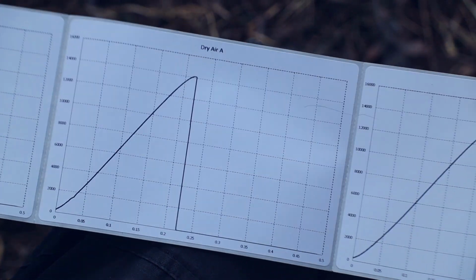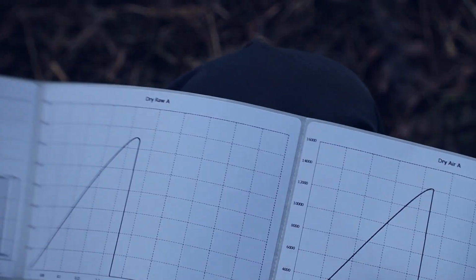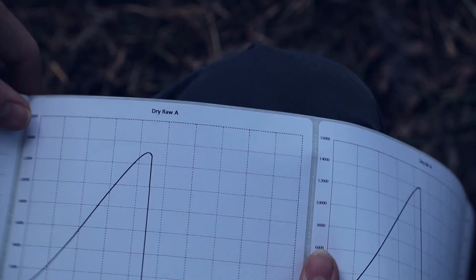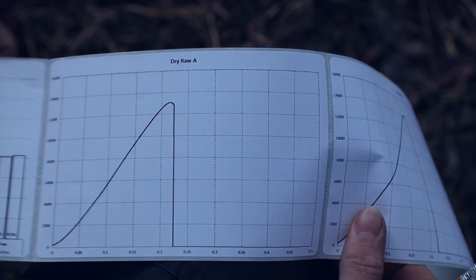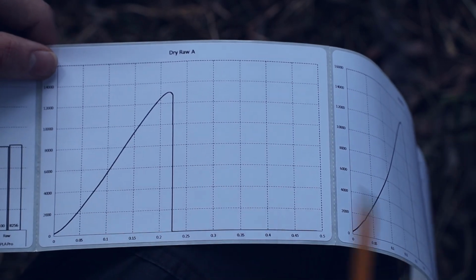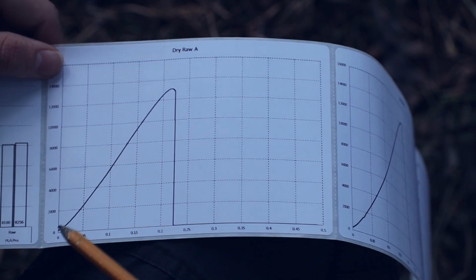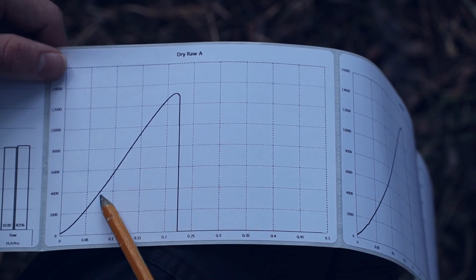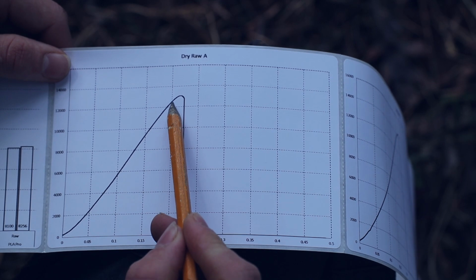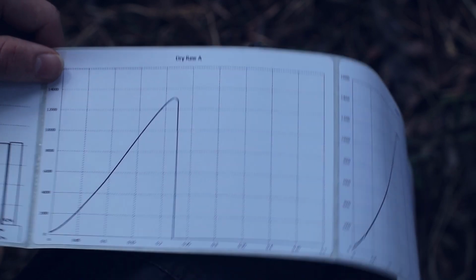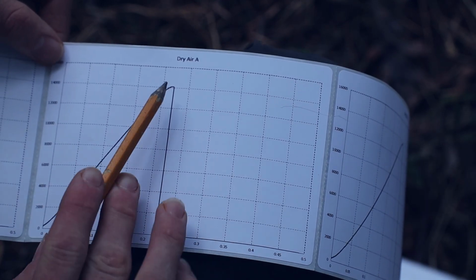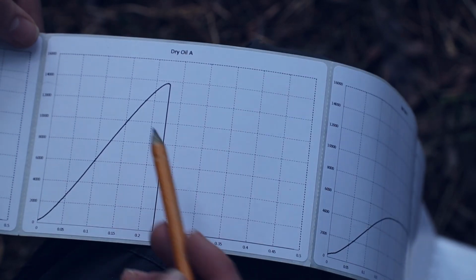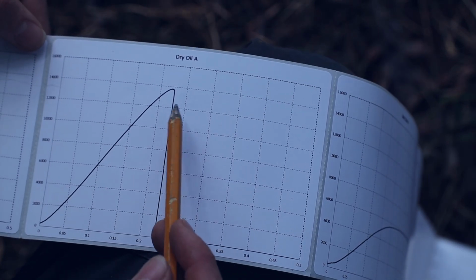Let's jump into our stress strain curves real quick and just go over these and emphasize what we've been seeing so far. This guy right here, the stress strain curve for dry unannealed nylon, it almost looks brittle looking at this chart here, and it has a nice linear elastic deformation area, and then we have a very little bit of plastic deformation, and then we have a nice failure. Air annealed is actually very similar. The oil annealed kind of came out slightly in between the air annealed and the unannealed.